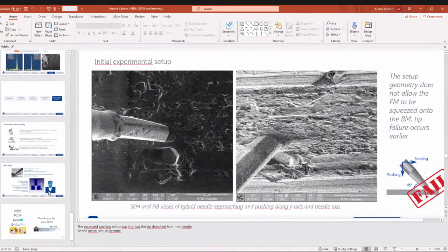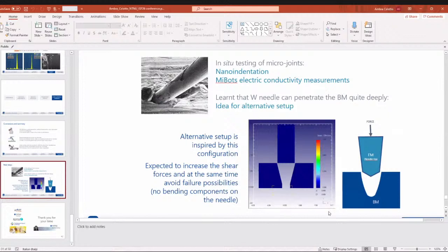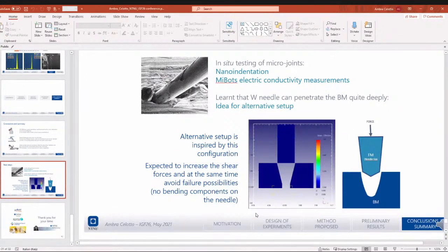And actually what we are trying to develop now is this new setup, in which the hybrid needle will be pushed quite perpendicularly to a hole that is dug in the base metal plate here. And we are trying to mimic this simulation here. We expect that this setup will enhance the shear stresses between the filler material tip sides and the hole sides in the base plate. Also, this setup can prevent the bending. So yes, I think that this new configuration will work better. So good luck. Yeah, thank you. We need that.